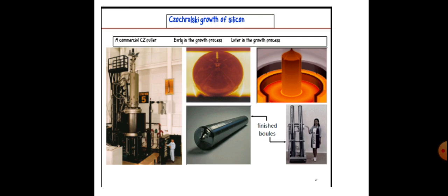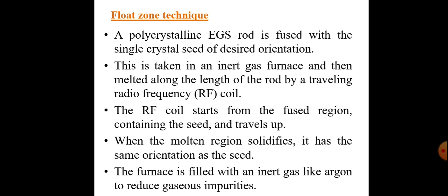Similarly, we have to obtain a single crystalline ingot by the FZ process. Here also, the raw material used is polycrystalline electronic grade silicon. The key principle behind the Float Zone technique is that the impurities present in the electronic grade silicon have higher solubility in the molten state of silicon compared to the solid state. That is the principle here.